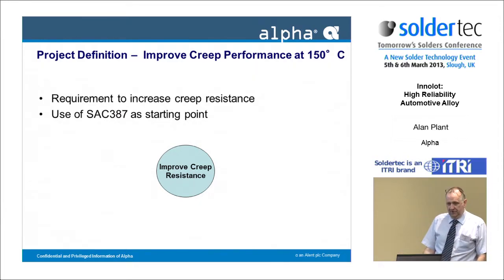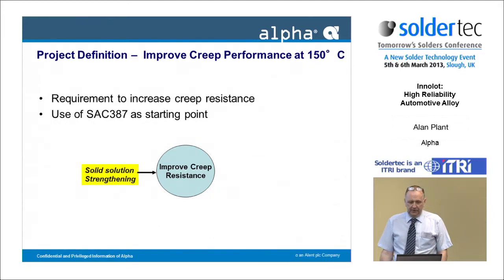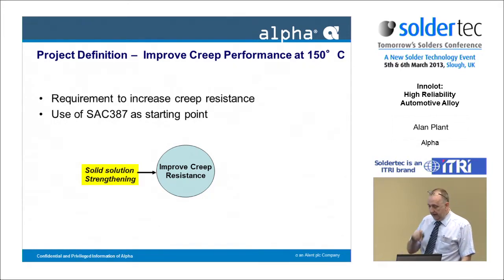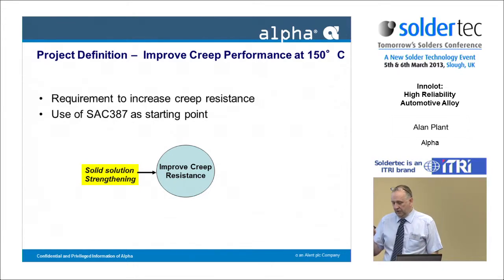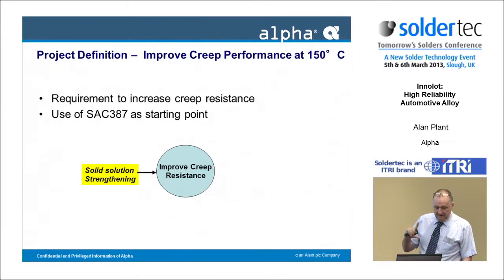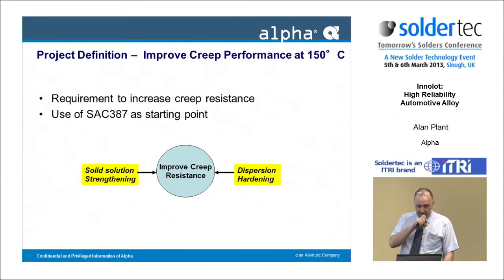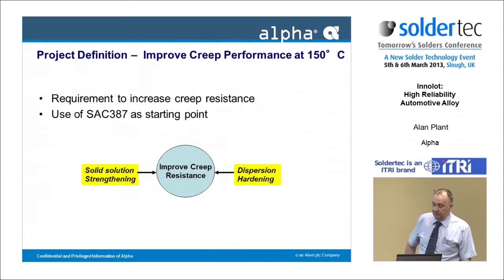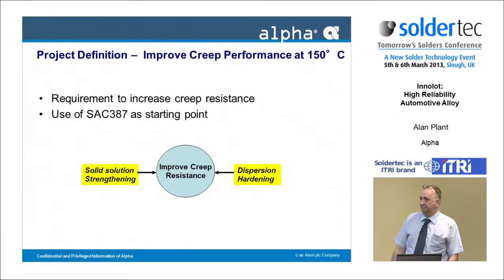alloy. So what they looked at to improve creep resistance, and how they did that, they looked at solid solution strengthening. So in this case, putting elements in that either had larger or smaller atoms that inserted themselves into the atomic or lattice structure, and in effect bent that structure, for want of a better expression, and then dispersion hardening, so where you were actually precipitating phases or materials out. But both methods really were there to stop dislocation movement and therefore creep mechanism.